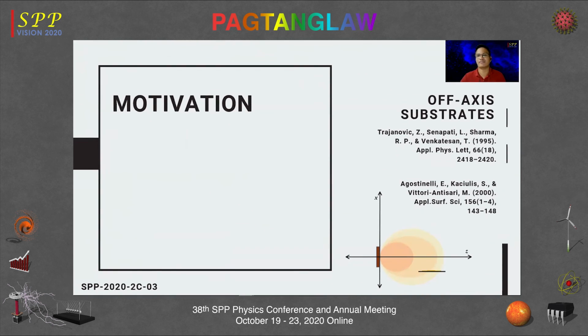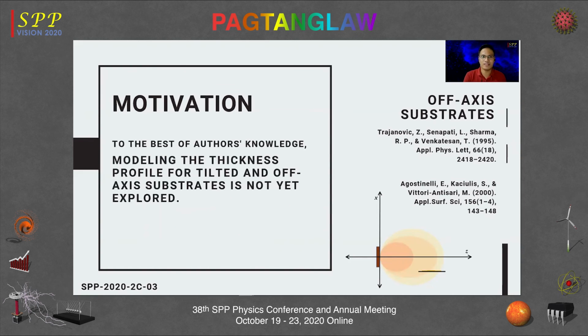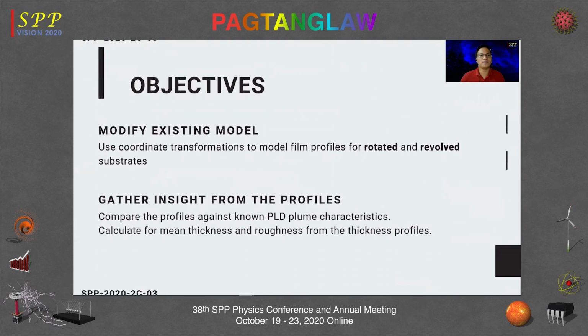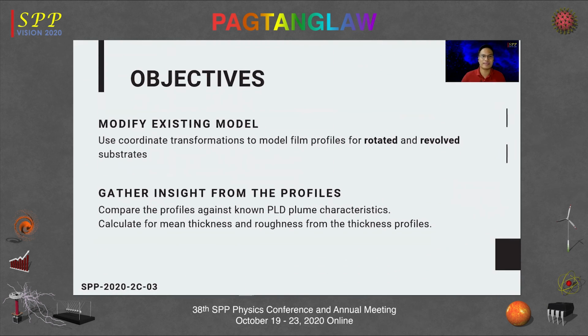As early as 1995, there are several groups that have been exploring other deposition geometries to minimize the deposition of particulates that normally have a trajectory along the center of the plasma plume. These off-axis substrates have thickness profiles that are significantly different from the typical center peak thickness profiles in the conventional PLD geometry. To the best of the authors' knowledge, modeling the thickness profiles for tilted and off-axis substrates is not yet explored. What we want to do is to modify the existing model.